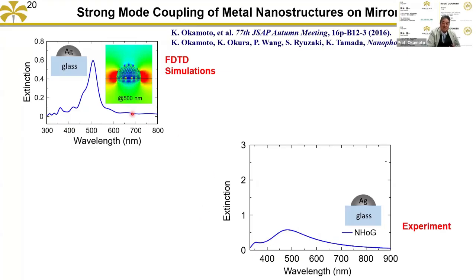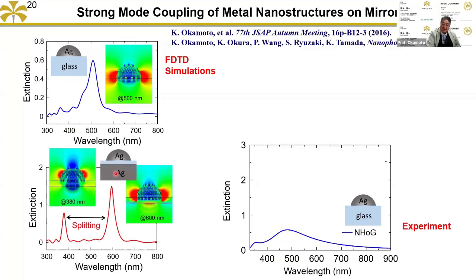But if we put this structure on the metal substrate with the spacer and the hemisphere, in this case these two modes interact with each other, and it's some kind of strong coupling. The two modes couple to each other, so it's a hybridization of the two modes. Then it splits into two modes. By controlling this size, we can control the splitting. And also, the good thing is that the peak becomes much sharper and much stronger.